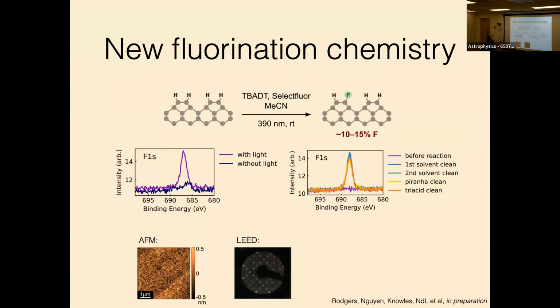So we can do one of these hydrogen atom transfer reactions to put fluorine on the surface. You see a very clean fluorine peak. We can do basic hypothesis testing, like if I don't turn on this light to do the photocatalysis, we don't see this fluorine peak. And I see that this fluorine is very, very robust to many different things that I can throw at the surface, including boiling in perchloric, nitric, and sulfuric acid for an hour. So we really think this is covalently bound to the surface.